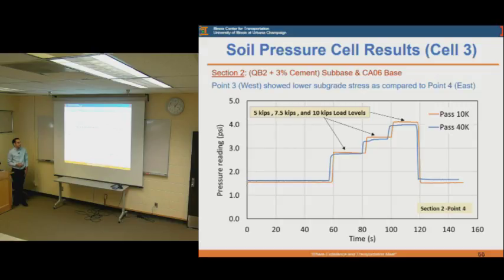This is similar to the results shown from cell 3 this time, the 2 test sections that were instrumented from cell 3. In a similar manner, static loading, 5 kip, 7.5 kip, and 10 kip. This time you see much less noise because we were able to handle the noise better. We were able to turn off the engine of Atlas while we were doing the measurements, which reduced the noise. And you see how the pressures were recorded up to the 10 kip load.